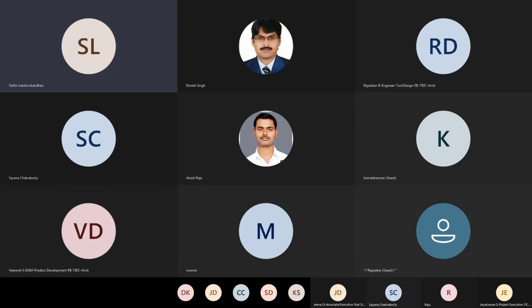Thank you. So Toolox is available in two different grades, Toolox 33 and Toolox 44. Toolox 33 is delivered at 300 BHN with a toughness of 100 joules. And Toolox 44 is delivered at 45 HRC with a toughness of 30 joules. It is produced by SSAB, who are known for producing advanced high-strength steels and quenched and tempered steel, with all the Toolox being produced in Sweden. And Swedish ME Steel is the exclusive provider for the Indian subcontinent and Middle East.